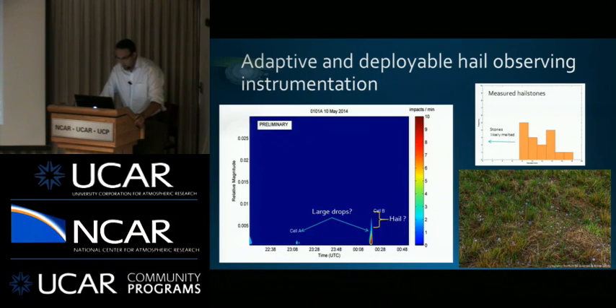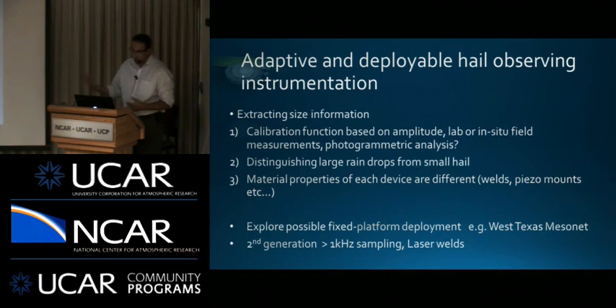And so the to-do list essentially is looking at distinguishing the large raindrops from the smaller hail. Could you do this, as I mentioned, with hail pads or the field measurement, or even photogrammetrics, so using the camera systems to look at individual impacts on the plates? What we've noticed is that the material properties of the devices are different. It's the quality of the welds, making sure your piezo mounts are essentially as uniform as you can make them.